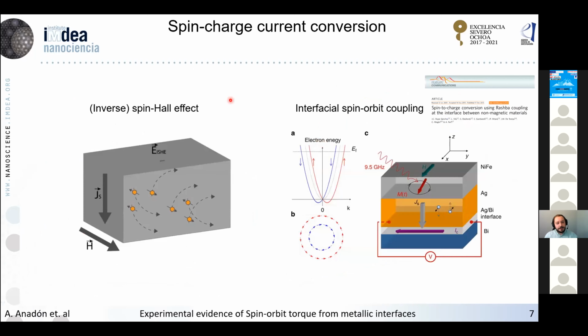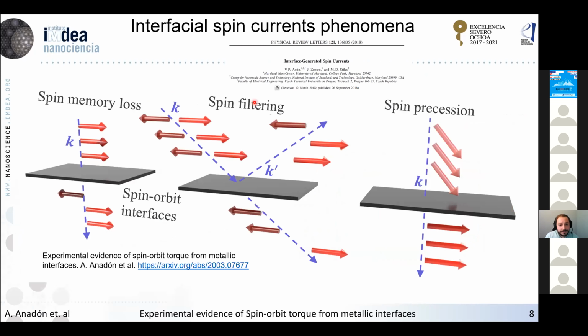Okay, so I've talked already about the spin Hall effect, and its inverse counterpart is basically when you have a spin current, it gets converted to a charge current or a charge accumulation. But it's also very interesting to notice that interfaces with a spin orbit coupling can also give rise to this spin to charge conversion. And basically, recently it has been predicted that when you apply a charge current in the in-plane direction of spin orbit interfaces, there are ways that spin currents can be generated. Basically, we have selected the most relevant phenomena for this interfacial spin current.